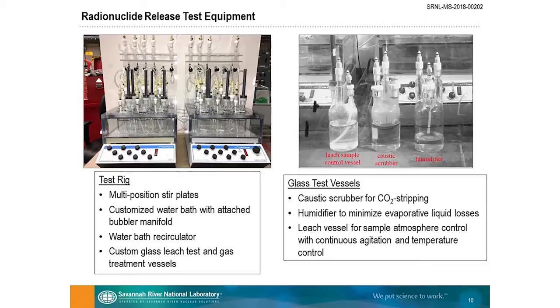So it ended up being a fairly complicated piece of equipment to operate in the cells. But bottom line, each sample sits over a stir plate. We stirred the samples with magnetic stir bars. We used a water bath recirculator that's not shown to control the temperature, to deal with the temperature swings in the facility. And then we use customized glass leach test and gas treatment vessels, which are shown over here.